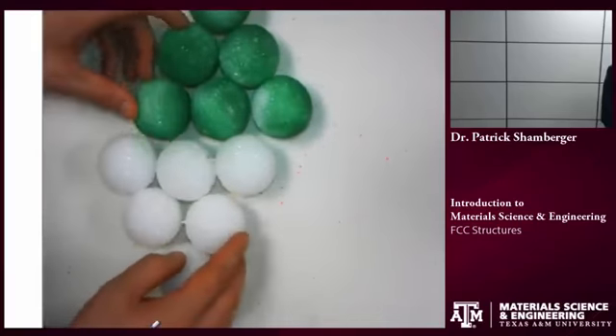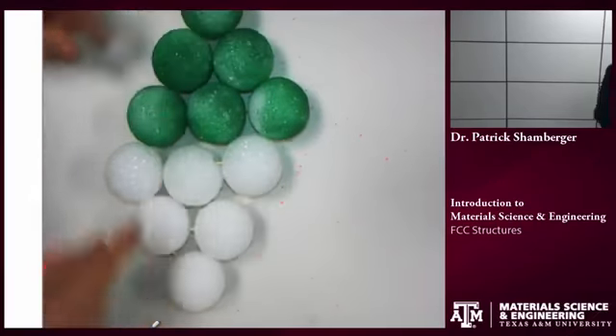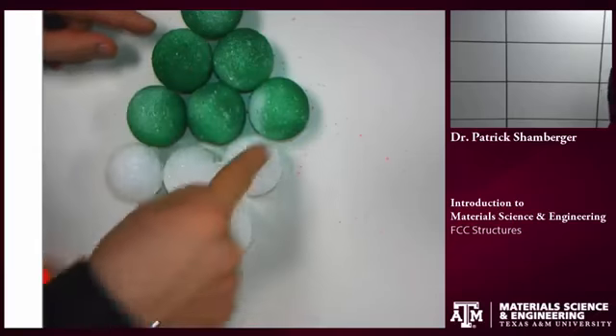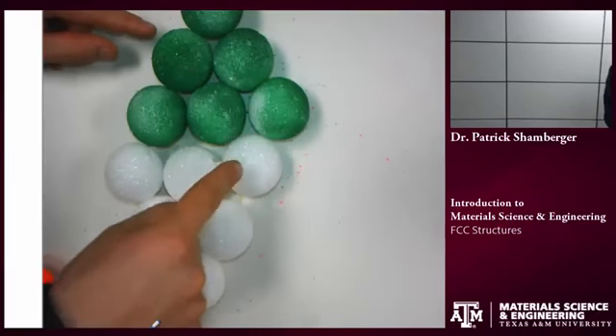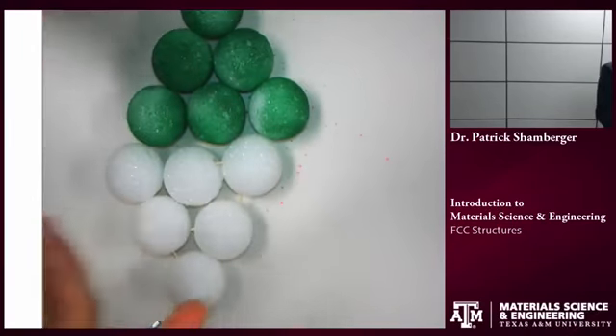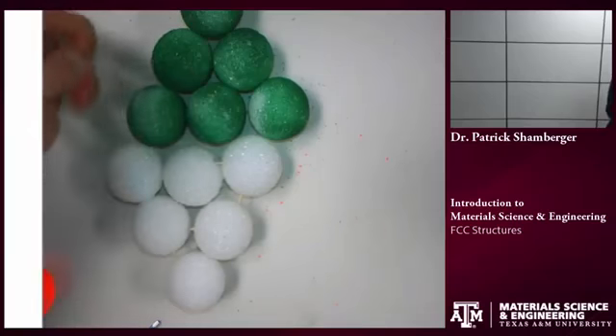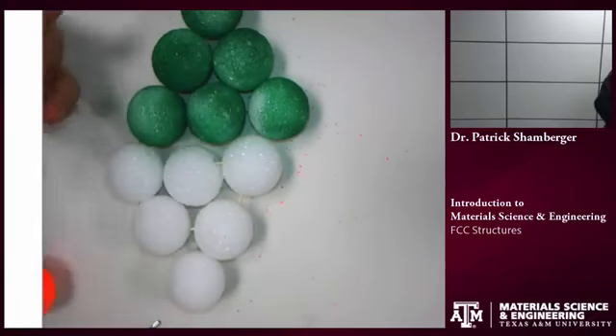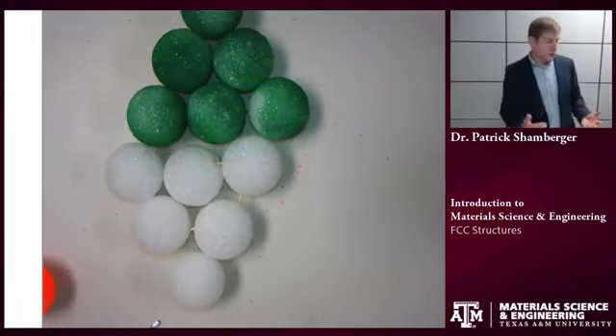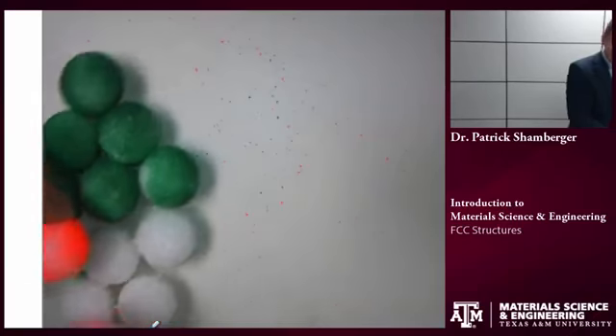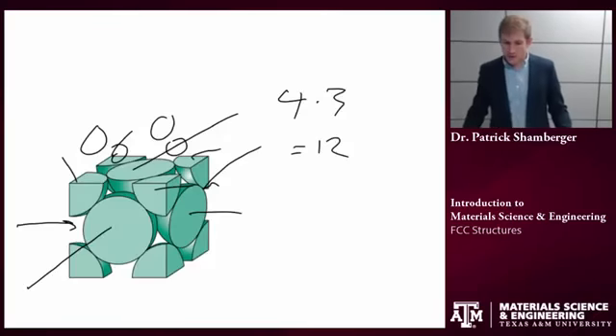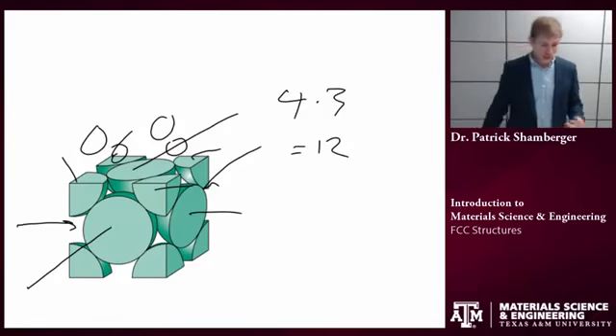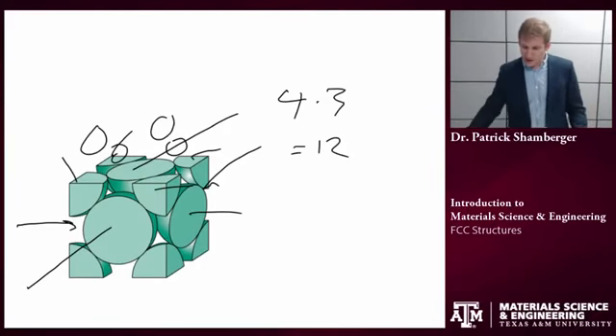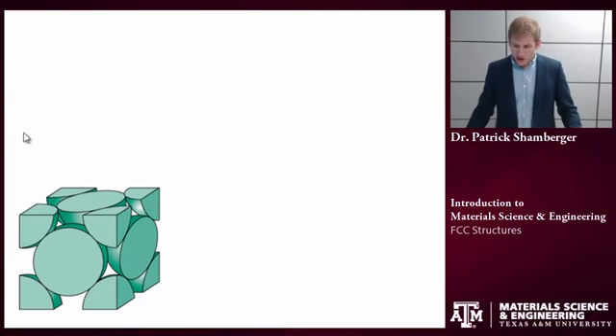And in the plane, if we borrow these two for a second, we can see one atom in the plane has 6 surrounding it. So again, this is just a different way to look at it. But we have 3 below, 3 above, and 6 surrounding. So again, we end up with 12. So 2 different ways to look at the packing, the coordination number, but we're getting the same thing, which is good. Okay, let's try talking about different planes.